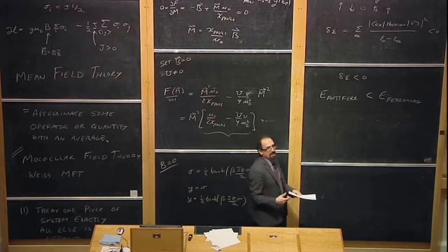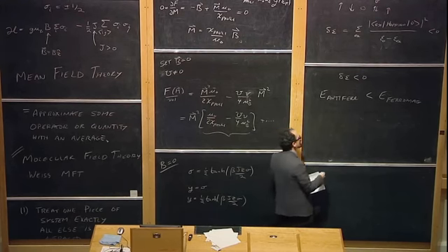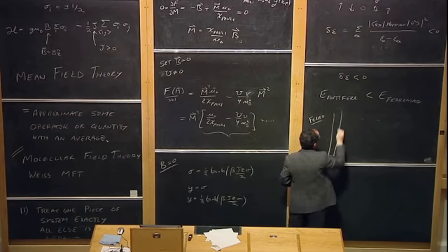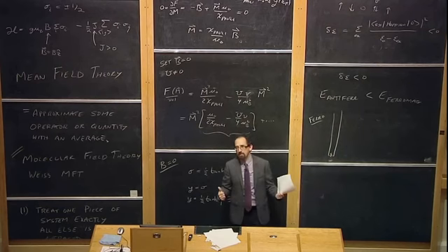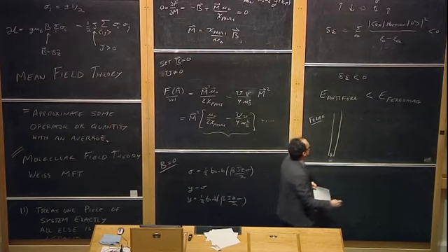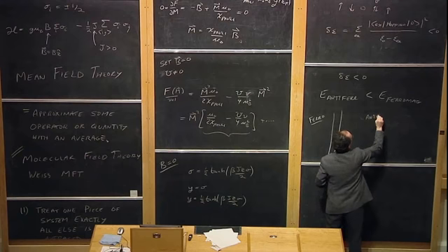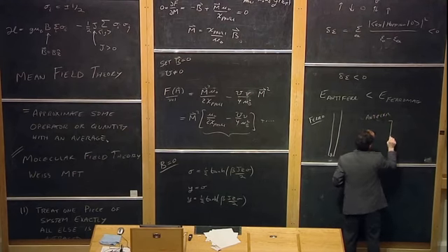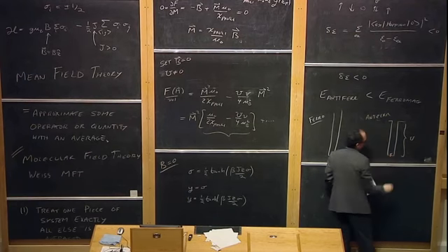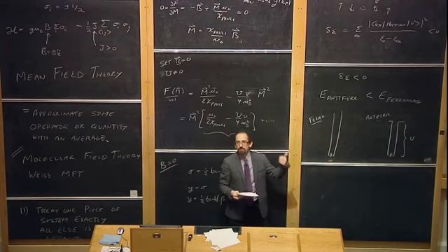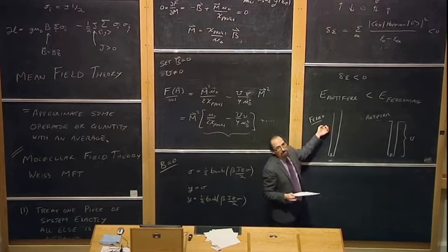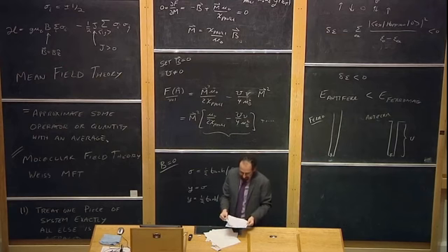Now, this might seem a little complicated, but let me rephrase what we just did. In the case of a ferromagnet, each electron is basically sitting in an infinitely tall well. It can't hop to the left, it can't hop to the right. That's absolutely forbidden by the Pauli exclusion principle. So you should think of it as an electron sitting in an infinitely tall well. Whereas for an antiferromagnet, you have an electron in a finite well. So the height of the well is only U. It can hop to the neighboring sites. It costs an energy U, but it can do it. It's not forbidden by Pauli. And the energy of the antiferromagnet with a finite barrier is lower than the energy of the ferromagnet with the infinite barrier. So the antiferromagnet is favored.